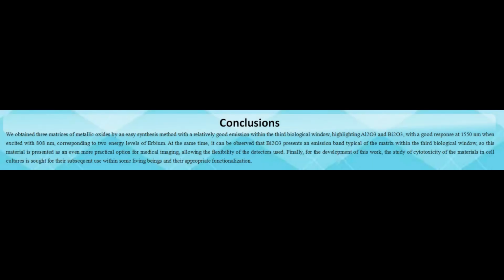We obtained three matrices of metallic oxides by an easy synthesis method with a relatively good emission within the third biological window, highlighting aluminum oxide and bismuth oxide with a good response at 1550 nanometers when excited with 808 nanometers, corresponding to the two energy levels of erbium. At the same time, it can be observed that bismuth oxide presents an emission band typical of the matrix within the third biological window, so this material is presented as an even more practical option for medical imaging, allowing flexibility in the detector used.